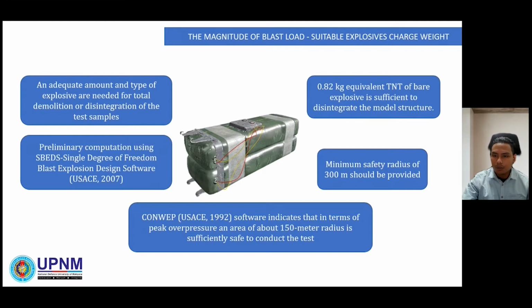With the same amount of explosive using ConWep software, it indicates that in terms of peak overpressure, an area of 150-meter radius is sufficiently safe to conduct the test. The peak incident overpressure drops to about 2 kilopascal within about 40 meters. However, considering blast fragments that can go much further, a minimum safety radius of 300 meters should be provided.